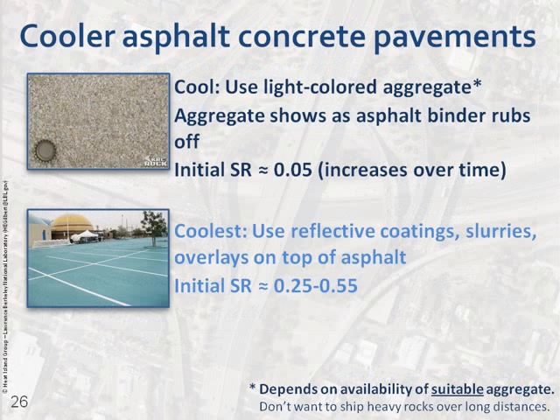If you use a light-colored chip on your chip seal, your pavement surface will actually have a higher solar reflectance. I know that when it comes to parking lots, as the aggregate starts to be exposed, it also might mean that it's time for a surface treatment. So the next idea is the coolest, and that's to use reflective surface treatment. There are many types that can serve in the place of a traditional seal coat that go on top of your pavement system, so they help preserve the pavement system itself. In that range, again, depending on the material used, from about 25% reflective to 55%.